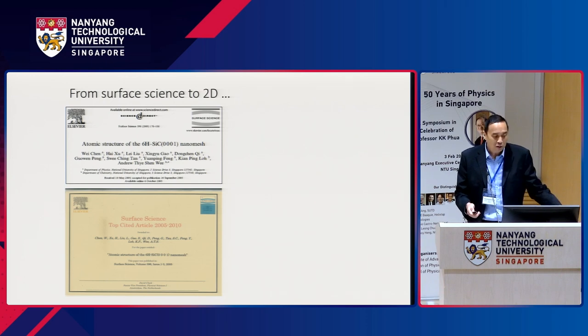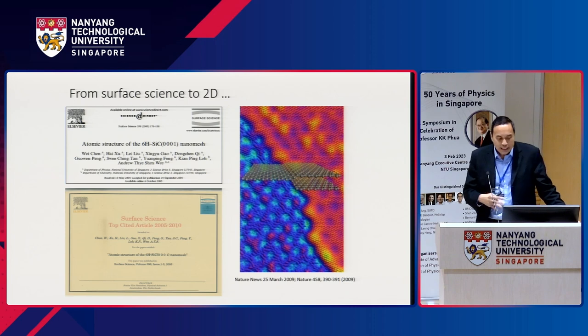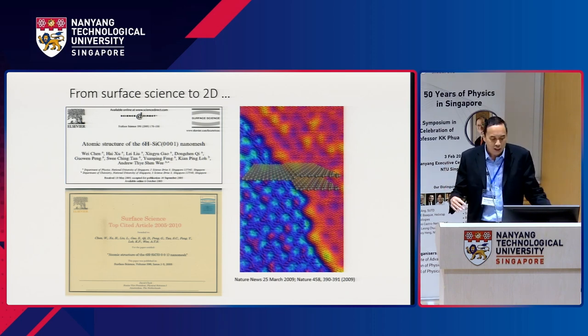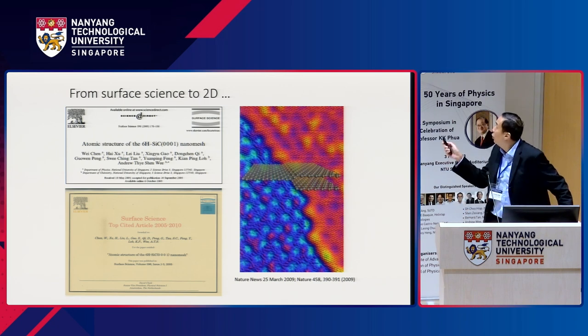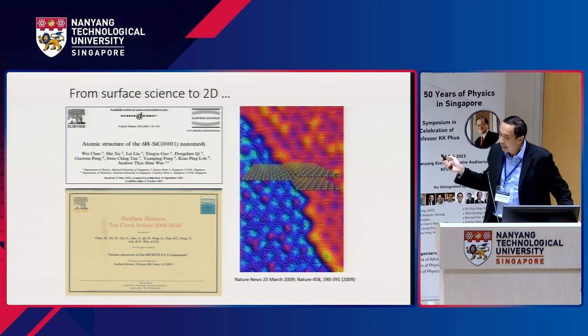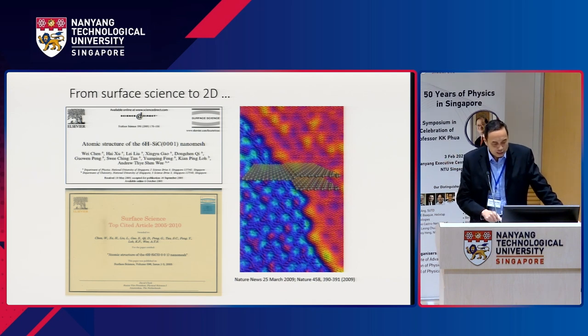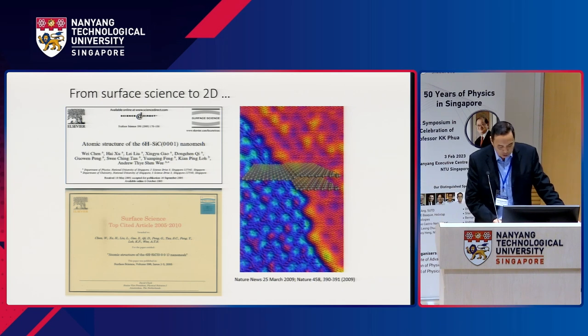And the reason wasn't because of the silicon carbide, it was because of the graphene, because when we heated it above about 1,500 degrees, we started to grow graphene above a 6x6 reconstruction we see just underneath, and it turns out it grows from the bottom up. You can see in this STM image the continuous layer of graphene on top. This side is bilayer, this is monolayer graphene. And this was reported in Nature News. So this was the most interesting paper that got us into the graphene scene.